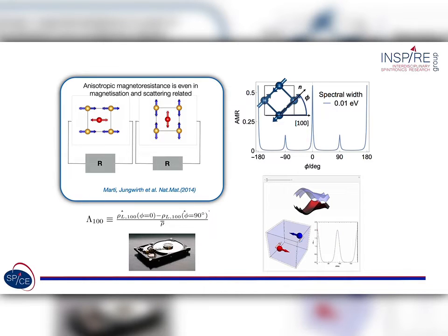The experiments, I should point out, were done in the tetragonal phase, where the actual crossings, these actual Dirac-like particles, are farther away from the Fermi surface, and the effects of the AMR on the transport will be more indirect and weaker by nature.